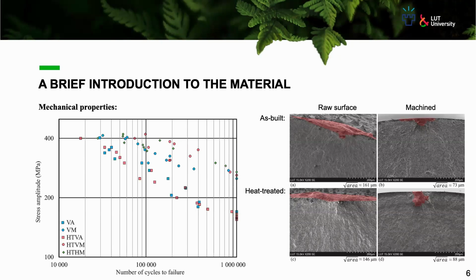And one interesting aspect of these precipitation hardening materials is that although precipitation hardening causes a huge increase in their quasi-static mechanical performance. In a significant number of cases, such hardening procedures don't show a noticeable increase in the fatigue performance of the material.